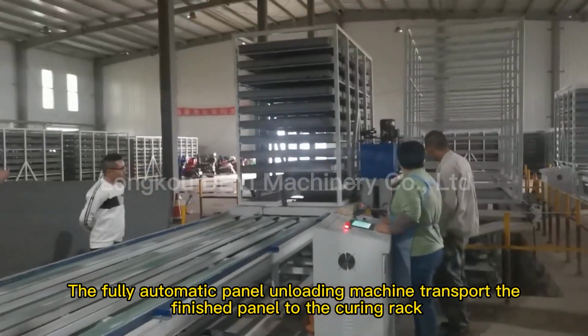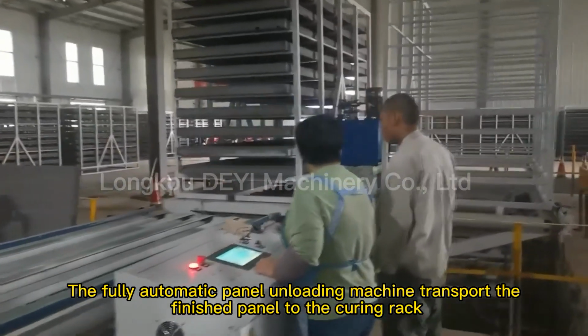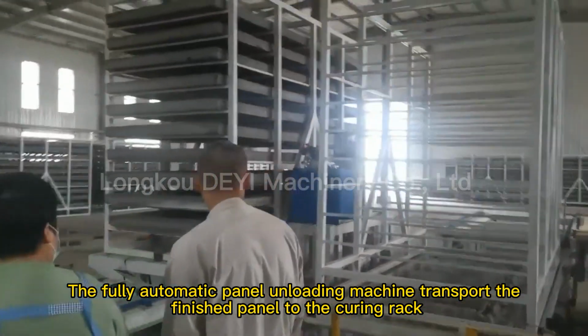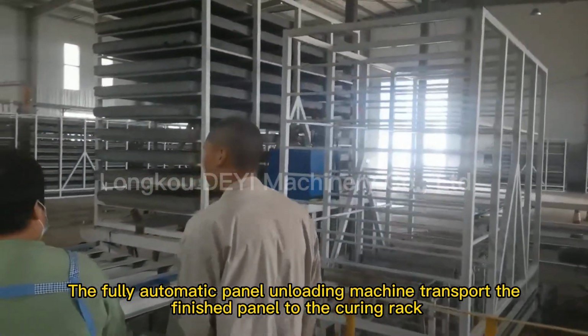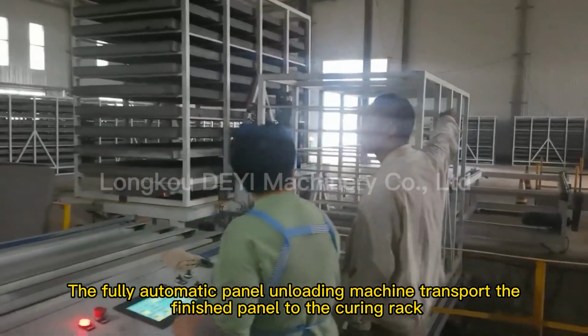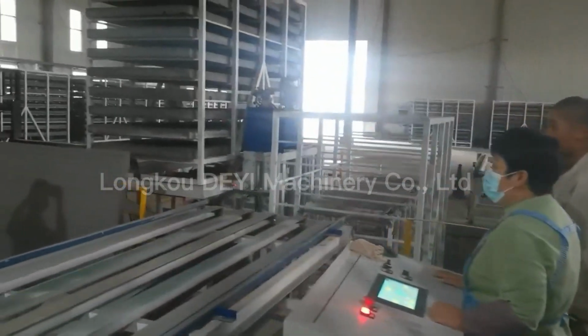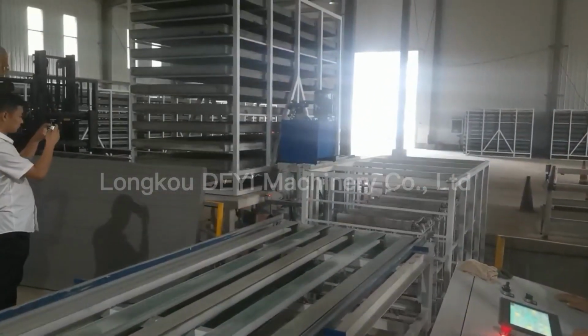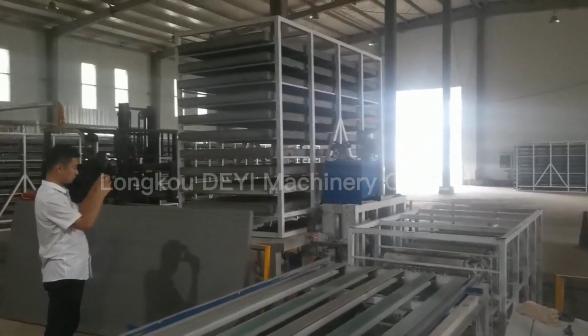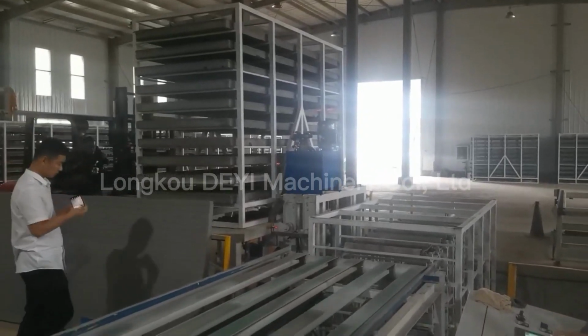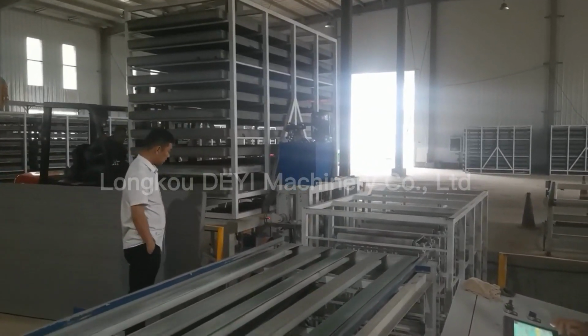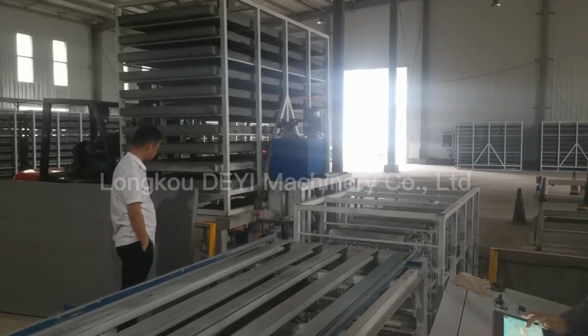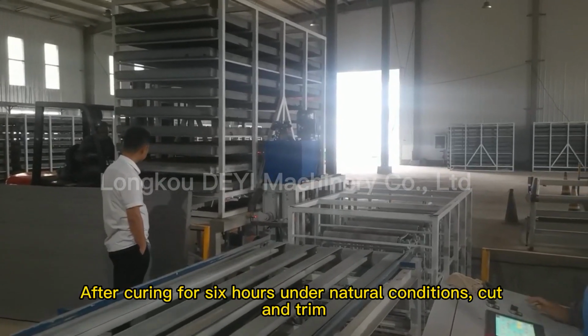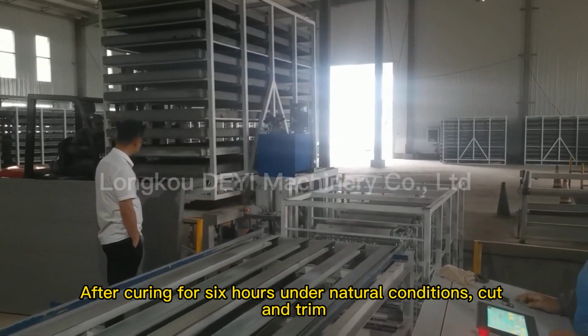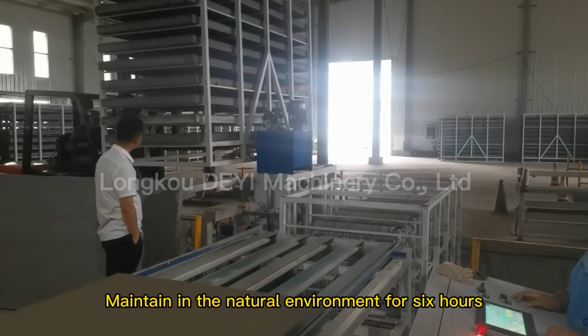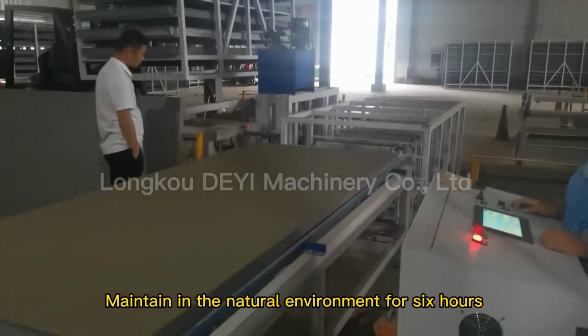The fully automatic panel unloading machine transports the finished panel to the curing rack. The forklift transports the curing rack to the curing area. After curing for 6 hours under natural conditions, the panels are cut and trimmed.